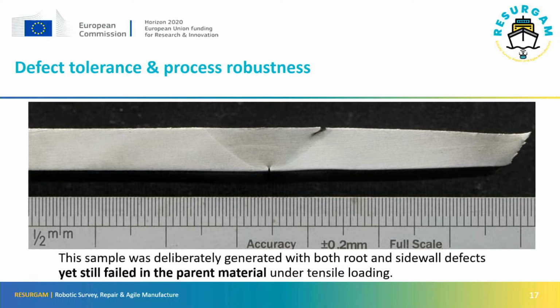We then subjected it to tensile testing and fatigue testing. And as you can see from this section through the test piece, the failure occurred here in the parent. So despite having two 1 mm long cracks, it was still stronger than the parent material. So it shows that the process can be very tolerant of defects. So obviously, you'd never want to put a weld like that into service, but if one day one did get into service in that condition, it probably wouldn't be a problem.